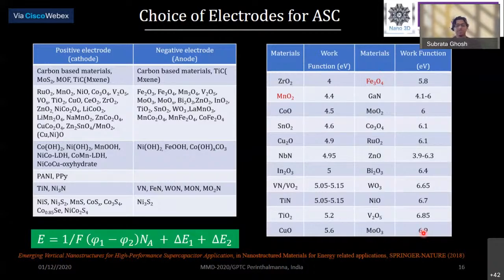But we should not look only at the work function difference. We also have to see how much charge they can store, meaning capacitance. For example, zirconium oxide is not good for storing a high amount of charge, and neither is molybdenum oxide. But manganese oxide, cobalt oxide, and tin oxide are good at storing a good amount of charge. On the other hand, iron oxide, ruthenium oxide, and manganese oxide show higher storage capacity than the other electrodes. So we have to consider several things and adjust the material to get the best performance from the device.